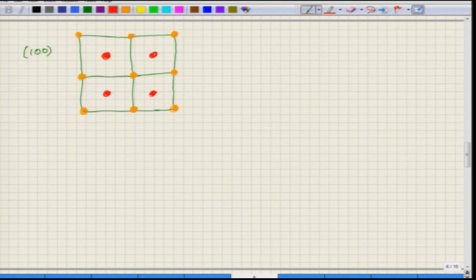So this is the 100 plane, and here the Burgers vector is in this direction. So this is your a/2. So from here to here is the a/2<110>. So now this is the shift that will take place. If there is an extra half plane on this 100, everything on this plane will shift with respect to the bottom plane by this much amount.